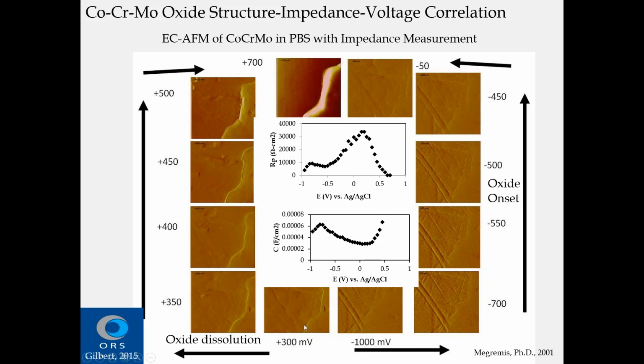And then if you go back to the bottom, starting at +300 and going onward, you can see how that oxide film suddenly changes its topography, its morphology. As we get up into the 400 and higher range, you begin to see this active corrosion taking place. That's corresponding to how the resistance of that oxide film varies with voltage. So this rising impedance corresponds with how the oxide film first starts and increases its thickness, and then begins to fall down again as that oxide transitions into this plus 300 and higher range. This correlation between the oxide film morphology and its properties is very, very good and indicates the behavior of cobalt chromium across the range of voltages in phosphate buffered saline.